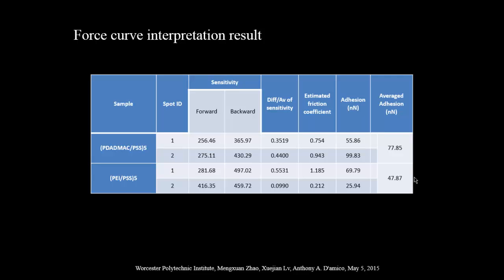This is a force curve interpretation result. From the result, we can see that the adhesive force from the strong and strong polyelectrolyte couple is higher than the adhesive force from the strong and weak polyelectrolyte couple.